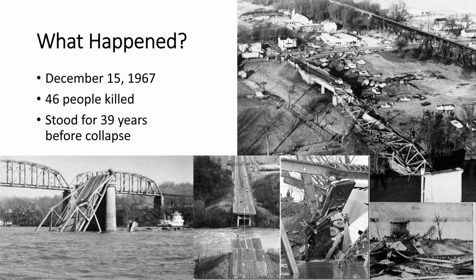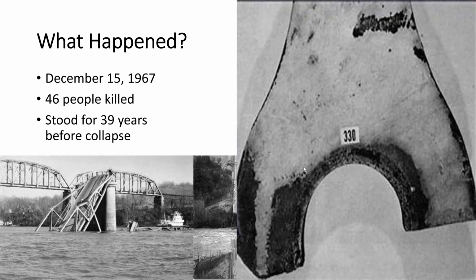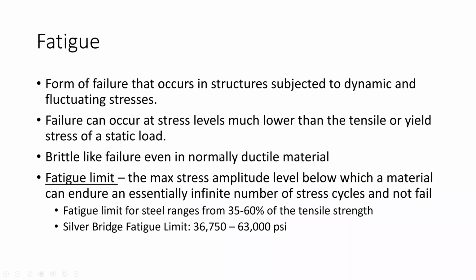So what went wrong? After a thorough investigation, it was found that a 1/8-inch manufacturing flaw in eyebar number 330 was the culprit. The propagation of this fracture and failure of this eyebar will be discussed in detail in the next few slides. Eyebar number 330 experienced high levels of fatigue up to the point of failure. Fatigue is a form of failure that occurs in structures subjected to dynamic and fluctuating stresses, often resulting in a brittle fracture, even in normally ductile material.